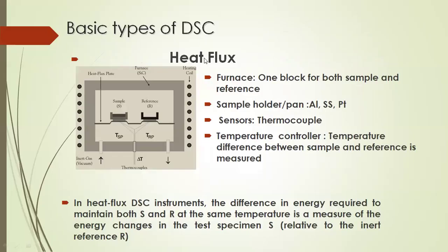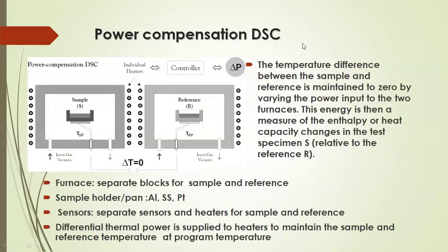What does heat flux DSC do? Heat flux DSC measures the difference in the energy required to maintain both sample and reference at the same temperature. That energy change is measured in a heat flux type of instrument. Here, the furnace is a one-block furnace. The sample holder can be aluminum, stainless steel, or platinum. And the temperature controller measures the temperature difference between the sample and reference. And second is power compensation DSC, where there are different sample blocks for sample and reference. The differential thermal power required to maintain these two at equilibrium is measured.